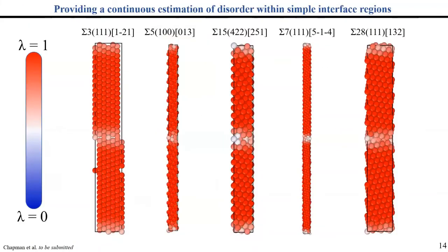So when we train it on just those bulk structures at different temperatures, how does it actually perform for the types of systems we want? This is the case of several contrived grain boundaries. You may say to yourself, well, there isn't really much of a difference in this order-disorder metric at the interface regions. And that's accurate for these types of grain boundaries, because these are very contrived, highly symmetric boundaries where we've essentially just cleaved a portion of the crystal and matched them up together.